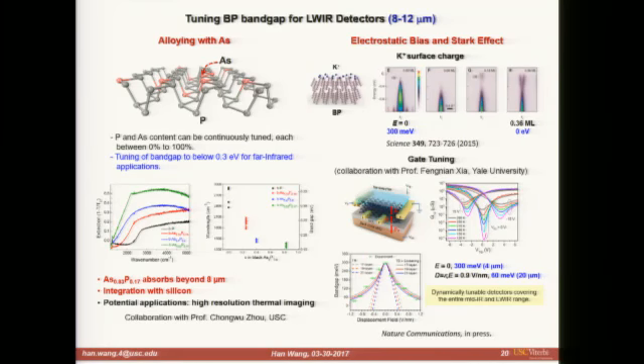In 2015, a group in South Korea published a paper in Science. What they did is dope the black phosphorus surface with charged potassium ions. These charged ions create a vertical electric field that induces band gap narrowing. As the electric field increases, as the potassium ion doping level increases, the band gap in black phosphorus reduces from 300 milli-eV all the way to 0.